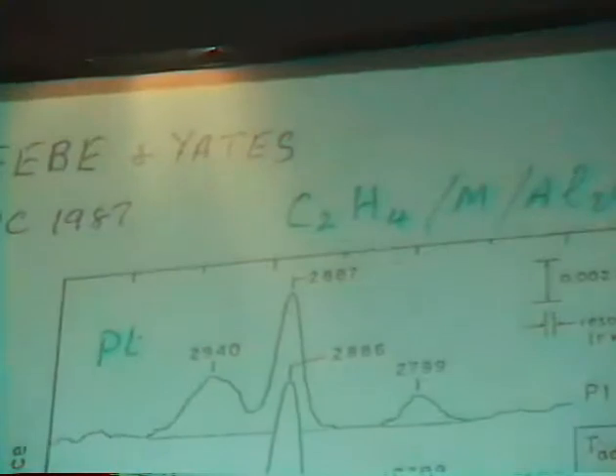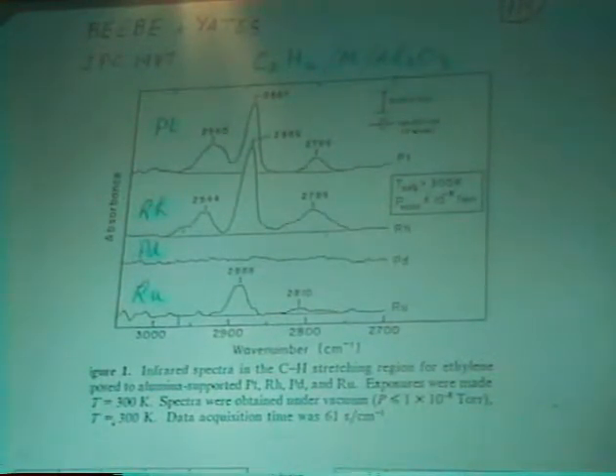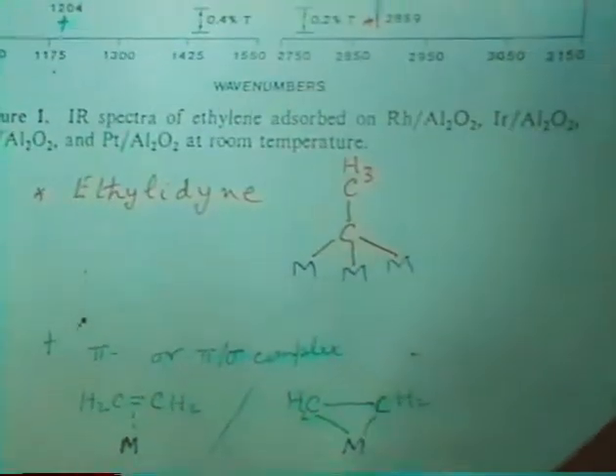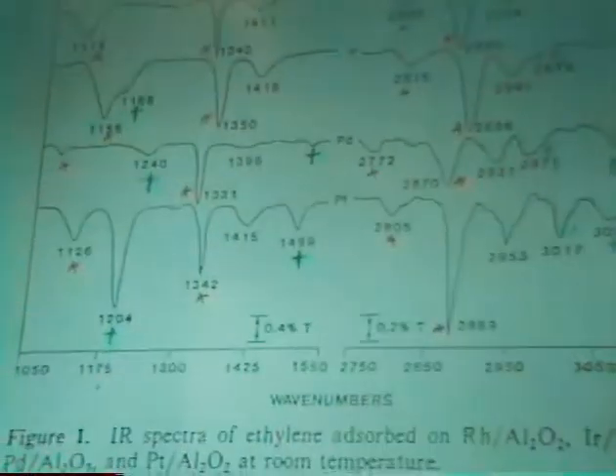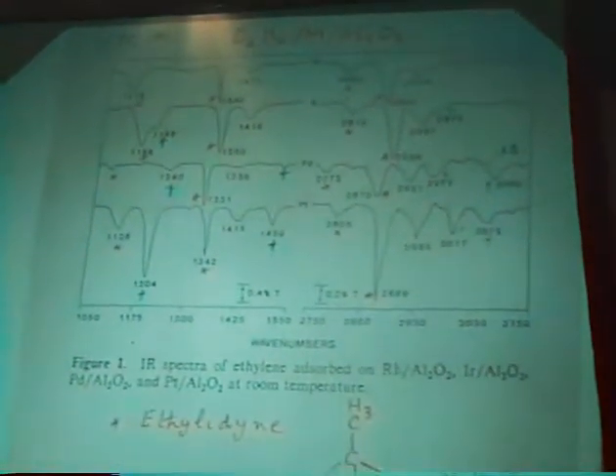And Tom Beebe and John Yates had also quite independently suggested the presence of ethylidyne as an explanation of the strongest features, and they went one further and actually got the CC stretching mode on their finely divided catalyst. And also Michael Trenery did very nice work, actually very much paralleling our work from low temperatures to high temperatures, seeing the conversion from disigma to ethylidyne, and also showing that a little sniff of hydrogen on the pi complex disappears very quickly.